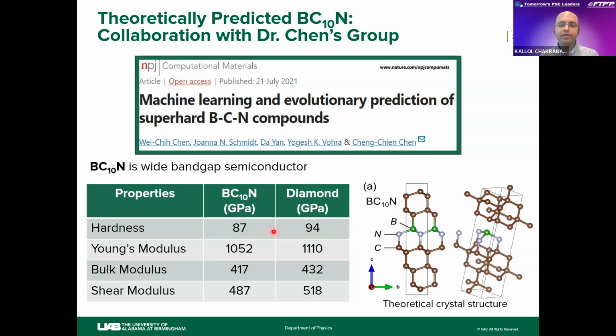At present, there is no superhard material with both high hardness and chemical inertness, because diamond oxidizes around 700 or 800 degrees Celsius. But for some applications we need to go beyond 2000 degrees Celsius, such as in extreme conditions. So we need a superhard material that is chemically inert. That's why we were motivated to synthesize this BC10N material, because it can resist oxidation up to 2000 degrees Celsius and has hardness comparable to diamond.